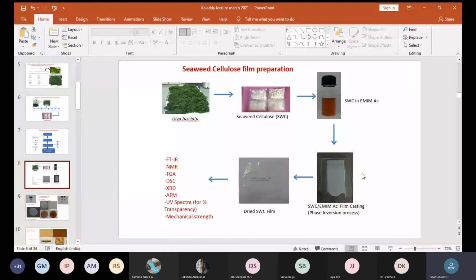That also we did, and we made the film that is of quite good quality like this one. But the only thing is, in carboxymethylated cellulose, we don't need any ionic liquid, because ionic liquid, people are telling it's green, but it does have a lot of negative inherent qualities that are yet to be explored or presented. So we try to make this carboxylated version that is quite soluble in water, and we made the film. We did the same procedure, only the carboxylation procedure we did, and we are able to get this compound and we prepare the film. And this is how it looks.